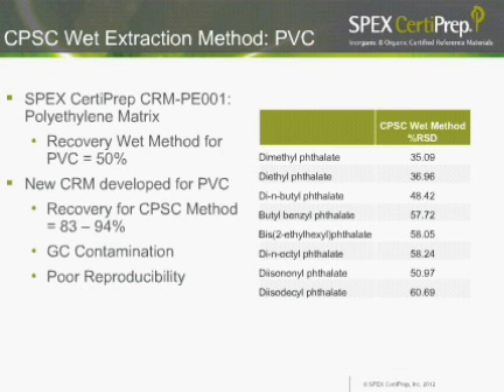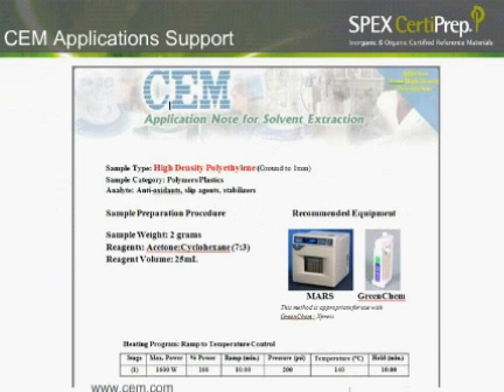So then we developed a CRM for PVC. We also ran it again using the Consumer Product Safety Commission's suggested method of the THF dissolution, and our recovery went up quite a bit, from 83 to 94%. But what we personally found was not all of our PVC material was precipitating out 100%, and we started having GC contamination issues, and our reproducibility started going very, very far away from the RSD. So when we did 10 subsequent injections, our RSD values climbed. So you can see they ranged from 35 to 60% RSD.